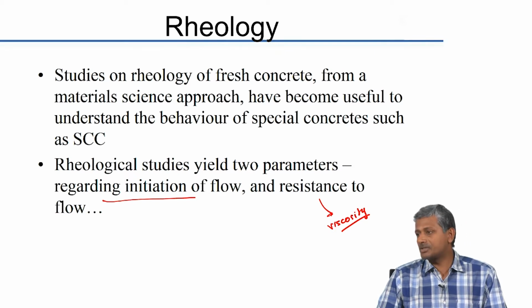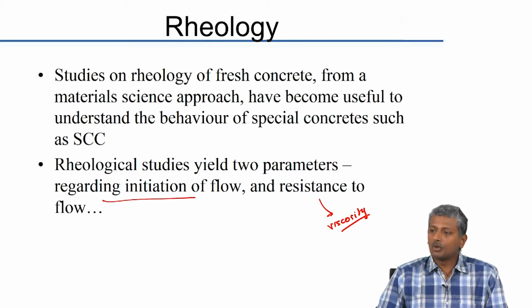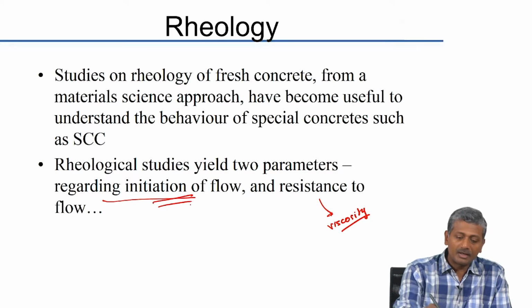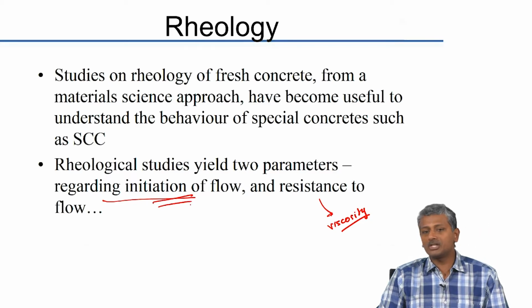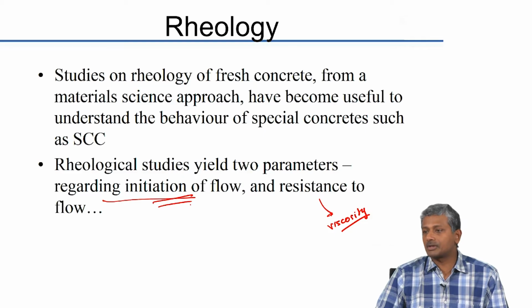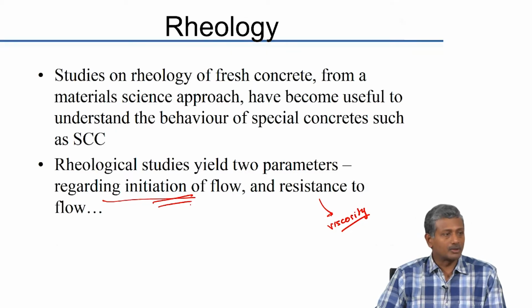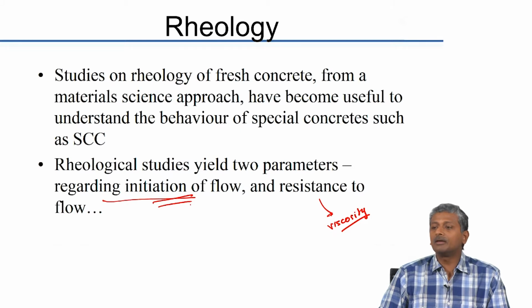Concrete obviously will have much higher viscosity than water, right. But one thing that you have not heard of when you talk about liquids is the presence of another factor which controls the initiation of the flow. In the case of water or oil, the moment you apply a shear to it, it will start flowing. But in case of semi-solid structures or suspensions, you may have to overcome an initial yield or shear stress to make the material start flowing. So, that is basically given by rheology.